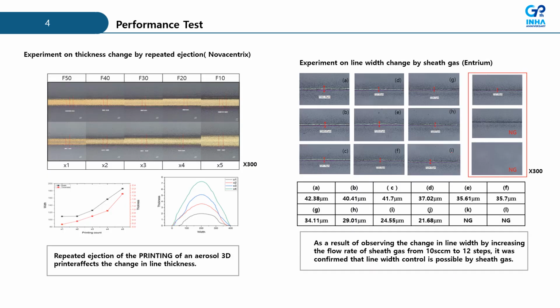The left picture is an experiment on the thickness change by repeated ejections. Repeated ejection of the aerosol 3D printer's printing affects the change in the line thickness. The right picture is an experiment on the line width change by sheath gas. As a result of observing the change in the line width by increasing the flow rate of sheath gas from 10 SCCM to 12 steps, it was confirmed that line width control is possible by sheath gas.